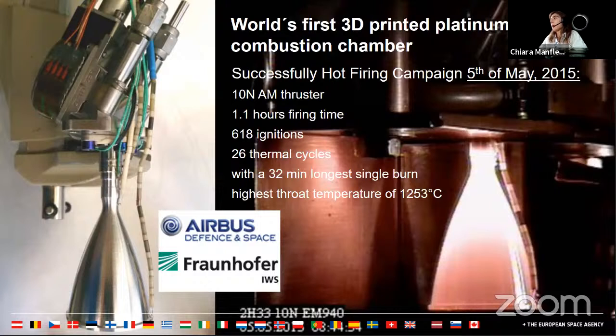They are normally made out of platinum, because of the thermal cycles that they have to go through, and because these structures cannot be cooled. So they normally use hydrazine. The pressures in them are up to a maximum of 20 bar. They go through lots and lots of cycles. In any case, in 2015, we had the first 3D printed platinum combustion chamber, which was successfully hot fired in a campaign.